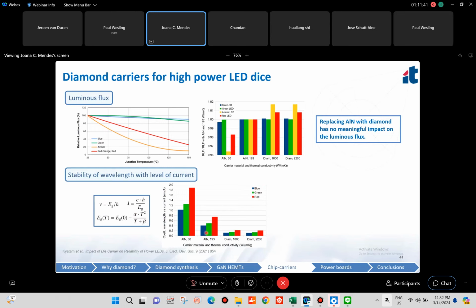And we observed that if we compare the best case aluminum nitride, which is this one, with diamond, if we had a red LED, we managed to decrease the coefficient of variation of the wavelength with the current from a bit more than 0.7 to approximately 0.2 for the red LEDs. And for the blue LEDs, this coefficient decreased from 0.4 to a bit more than 0.1. So we managed to stabilize the wavelength with the diamond carrier. And this can be quite important in applications where the wavelength stability is critical, for instance, for visible light communications, or even in some space applications.